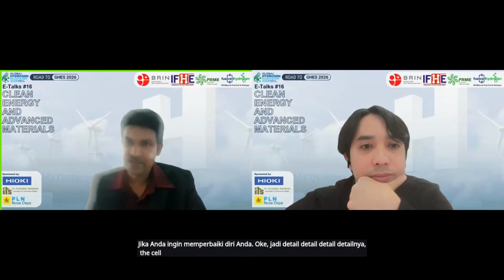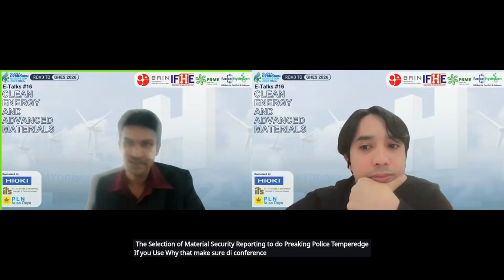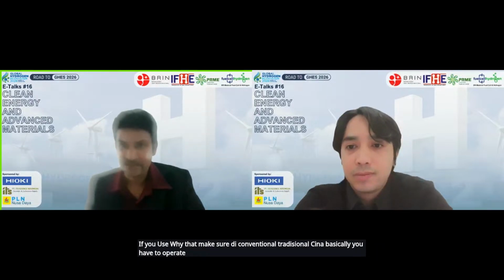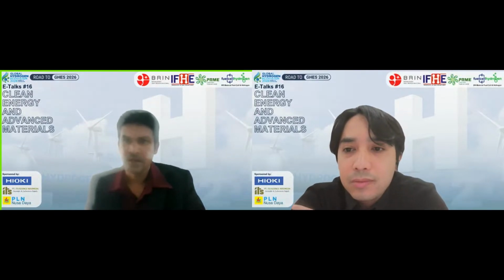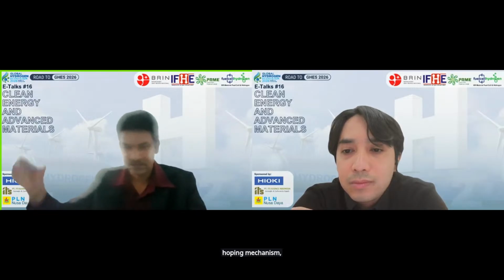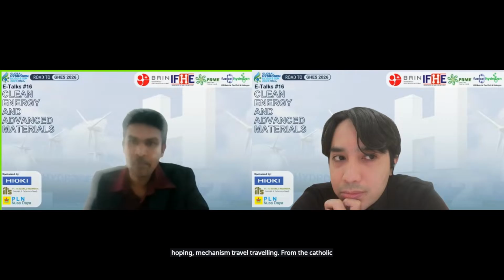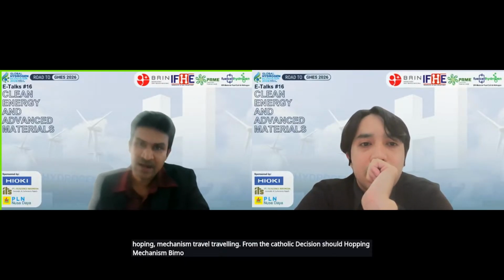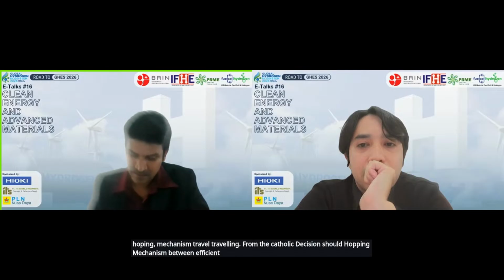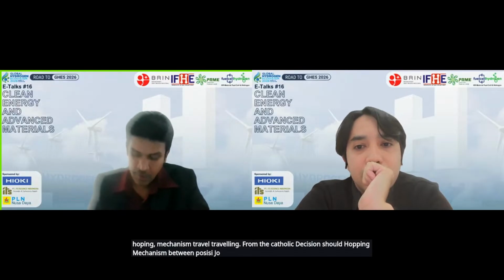The selection of materials is actually according to the operating conditions, temperature. If you use YSZ, the conventional, traditional zirconia-based material, you have to operate at a temperature of more than 800 for an efficient hopping mechanism. We call it the hopping mechanism, the oxygen ion traveling from the cathode to the anode of the solid oxide fuel cell. So the hopping mechanism will be more efficient at high temperature for zirconia-based material. For CGO, the hopping mechanism is efficient at a temperature lower than 600.